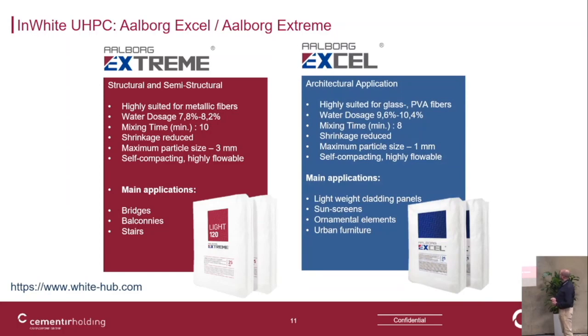After the Extreme, we developed a second product, the Aalborg Excel, with some slight differences. It's mostly about the maximum particle size, where we have a maximum 1 millimeter instead of 3 millimeters. And that allows to have even a better flow, and also for more complex formwork. This product has a better performance. And in this product, we oriented more into the decorative products, final products, such as cladding panels, sunscreen lamels, also ornamental elements or urban furniture.